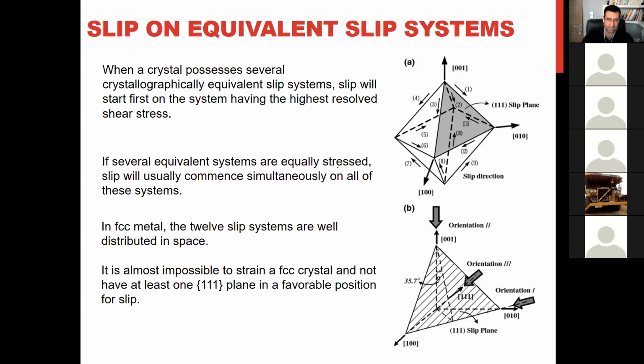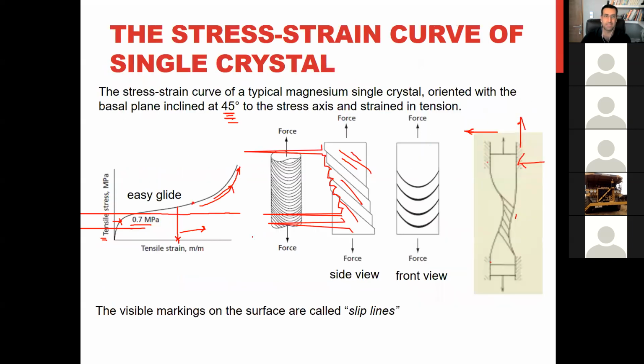So if you have a single crystal FCC and you are applying load in this direction, it means in this plane you have a slip, in this plane also you have a slip, and in these two other planes also you have a slip. It means several slip systems are activated at the same time, yeah. And what happens in this condition? Because for magnesium, just in this direction we have a slip, so we can see here easy glide, and nothing happened because just these planes are slipping on each other.